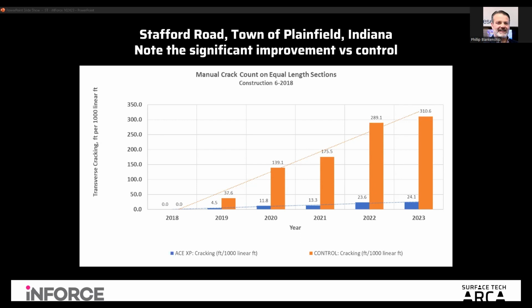And in this one, the control, of course, is the standard treatment with a 76-22, and the bottom is a 64-22 with the ACE XP single dose of fiber. And when this was done, the contractor simply added the Aramid to see what the cracking difference would be. What resulted, just to give you the quick end of the story, is this: today the city went back and, naturally, is specifying more, not just from a bar graph. You walk out and you see it, and it's just astounding.